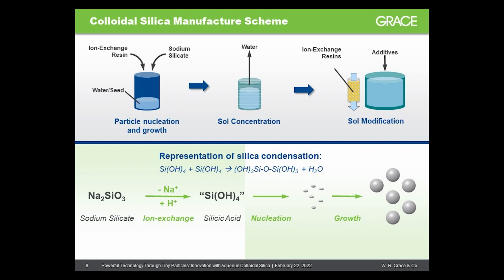The silanols undergo condensation reactions with adjacent groups to form growing silica clusters. Once these species form nuclei, deposition of additional silicic acid causes the nascent particles to grow. The sol is then concentrated either by evaporation or ultrafiltration. Post-modification of the sols can include ion exchange of the ions in the solution phase and surface modification by inorganic or organic additives.